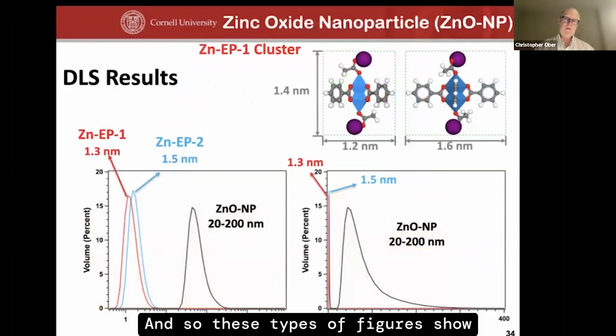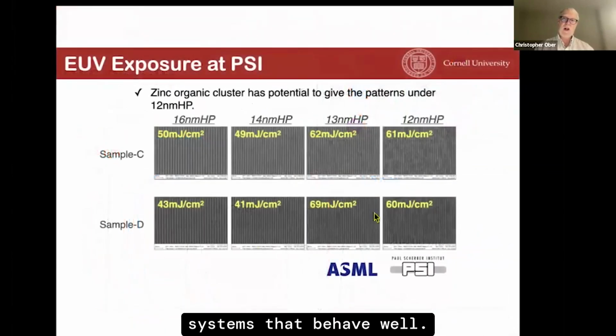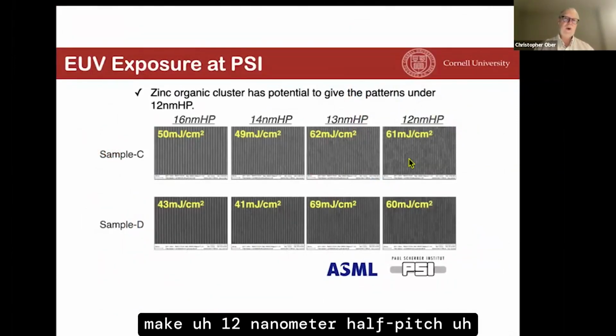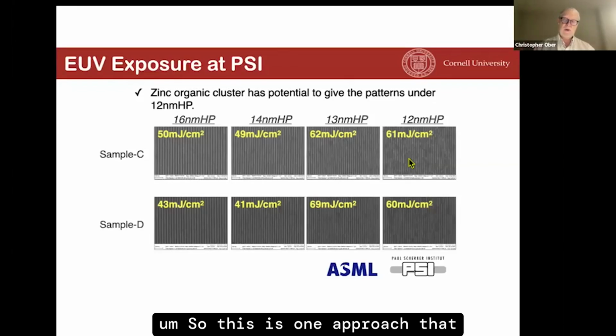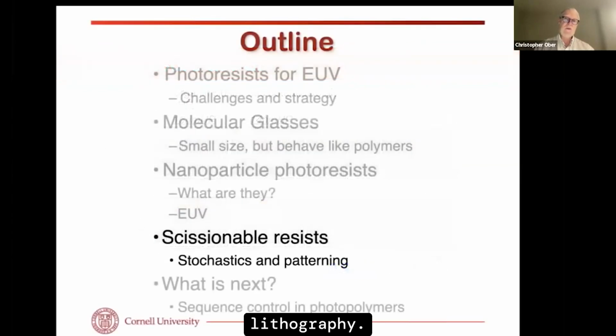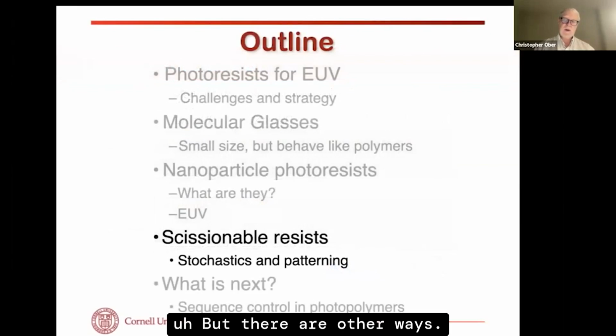And so these types of figures show that indeed with the zinc cluster, we could do the same thing we did with the zirconium, make very, very pure systems that behave well. And so suddenly we became able to make 12 nanometer half pitch features with these kinds of systems. So this is one approach that we've explored, using metal organic cluster molecular glasses to get high performance in EUV lithography. But there are other ways.